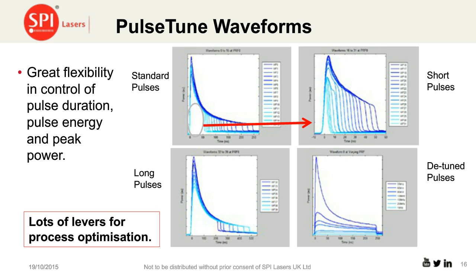What we can also do, and this is bottom right, is we can actually detune the pulses. So one of the things that I mentioned previously is each pulse is designed to operate at a critical frequency to give maximum peak power, which is the highest, sharpest pulse on that image. But if we then operate it at a higher frequency, the pulse energy decays or is reduced. Effectively the full width duration of the pulse remains constant, but we dull down the sharpness of the peak, which enables us to tune the laser to the application in question. And that's actually quite important for welding, as I'm about to show you.